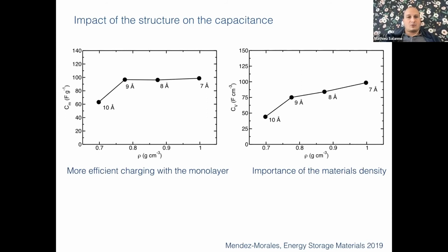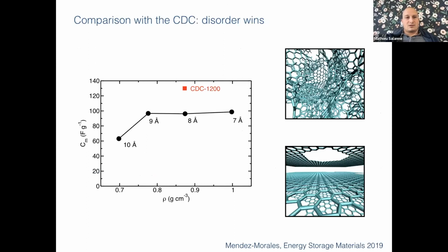But then what we observed is that the capacitance we get is lower than the one we had with the complex nanoporous carbons from before. And so this is a point I have put here. For the same ionic liquid, we have 100 farads per gram, while we could get 130 for a complex one. And so this was quite puzzling because we were expecting, as experimentalists, that the graphene would be a superior material, because it has all the good characteristics. And so again, we tried to understand at the microscopic scale what was the origin of this effect.